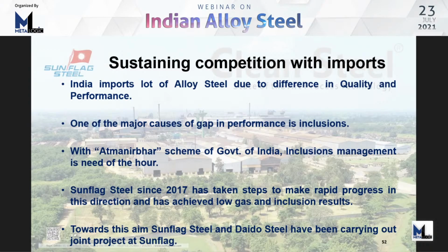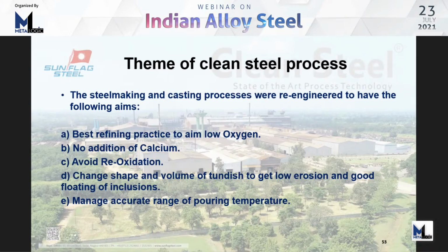Sunflag Steel since 2017 has taken steps to make rapid progress in this direction and has achieved low gas and inclusion results. Toward this aim, Sunflag Steel and Daido Steels have been carrying out joint project at Sunflag. The steel making and casting processes were engineered to have the following aims: best refining practice to aim low oxygen, no addition of calcium, avoid reoxidation, change shape and volume of tundish to get low erosion and good floating of inclusions, and manage accurate range of pouring temperatures.